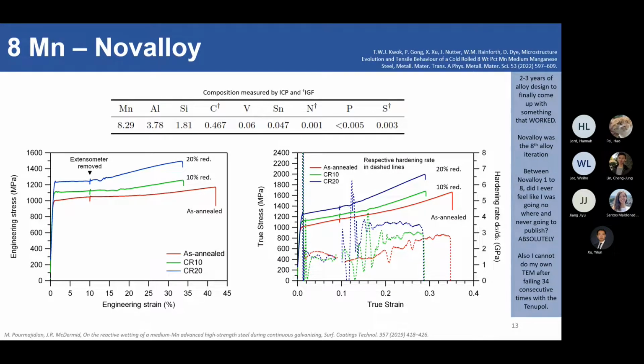So we're coming down from 12 to 8. So this is 8 manganese steel that I lovingly call Novalloy. It is the novel alloy, hence Novalloy. So this is the 8 manganese steel, but this is also quite a highly alloyed steel. You've got quite a high aluminum and silicon content. Also, similarly, you've got quite a high carbon content. We've deliberately added tin, as it's been reported that tin helps the galvanizability of this steel.